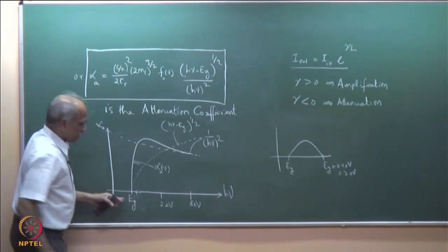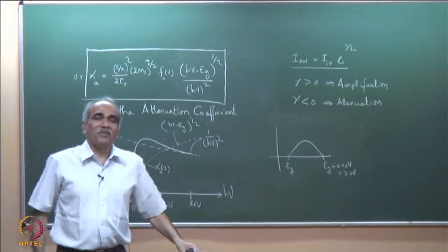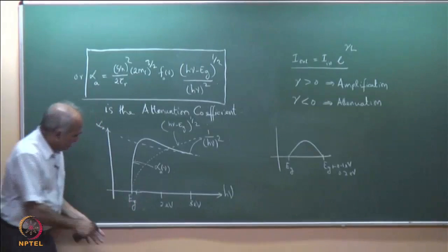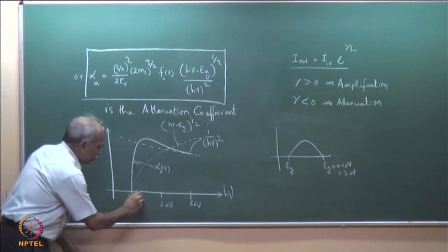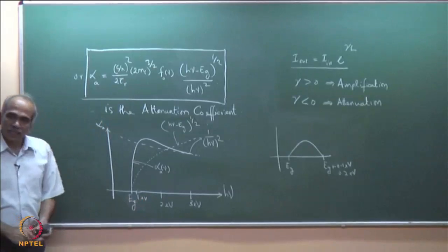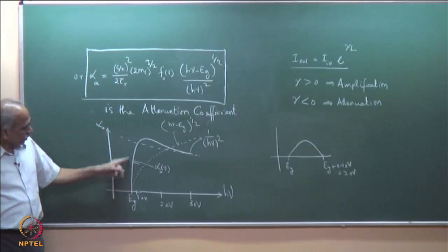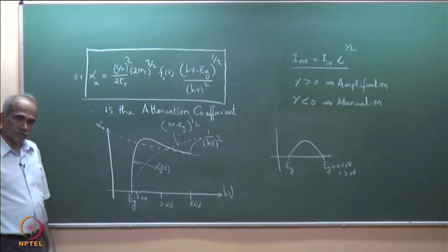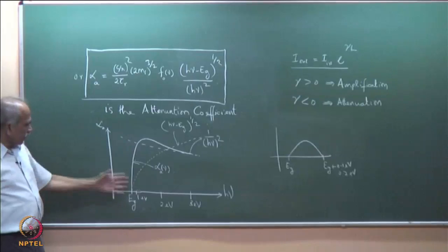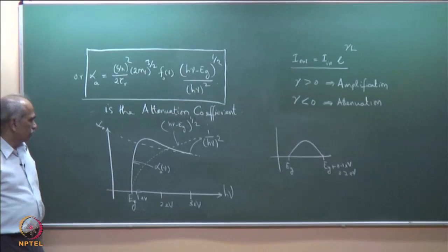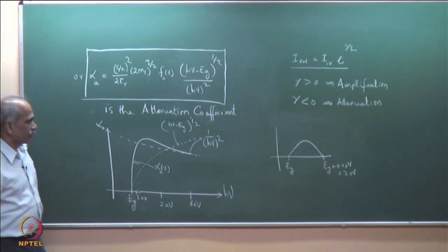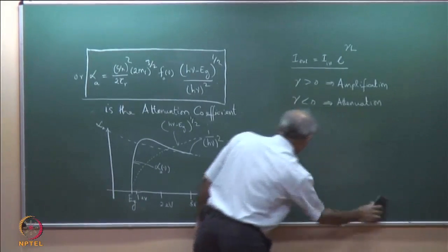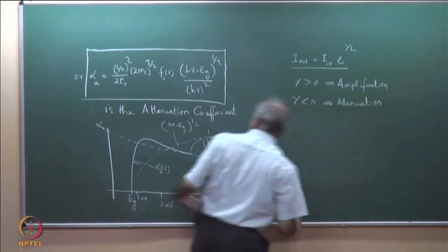Does not matter, because there are materials with Eg less than 1. If you take germanium, it is 0.66 eV. So, from Eg, this starts from Eg. So, this is 1 eV here. Yeah, please correct it, that it starts from Eg, goes up, and then has a variation like this. This is what we expect to get in a semiconductor, the absorption spectrum of a semiconductor. But in practice, if you see the absorption spectrum, I will draw typical absorption spectrum just by the side here.